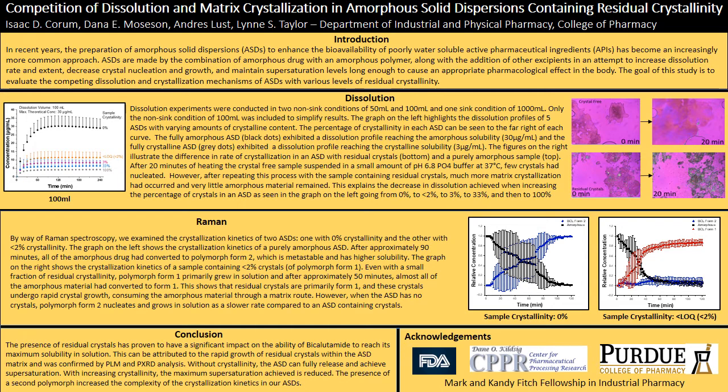Supersaturation refers to having more drug molecules dissolved in solution compared to the crystalline solubility. An amorphous form of a drug has less structure between individual molecules compared to the crystalline form. This lowers the amount of energy needed to strip drug molecules from the matrix and dissolve in solution, and supersaturation can then be achieved. Crystal nucleation refers to the spontaneous conversion of amorphous drug to the crystalline drug in solution. These crystals can then grow, reducing the dissolution profile of the drug.